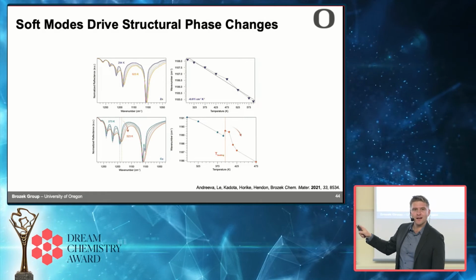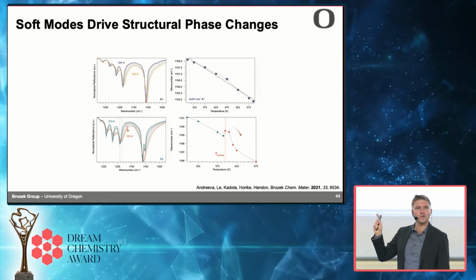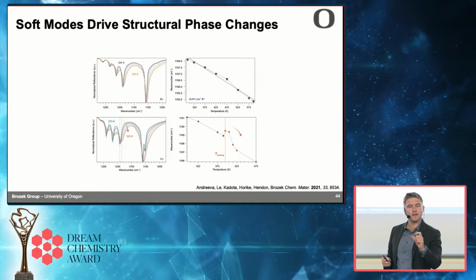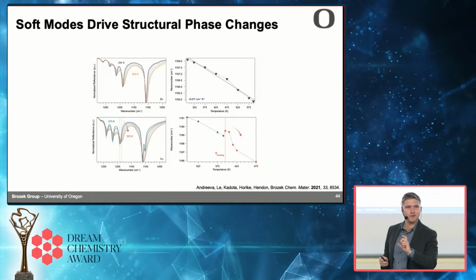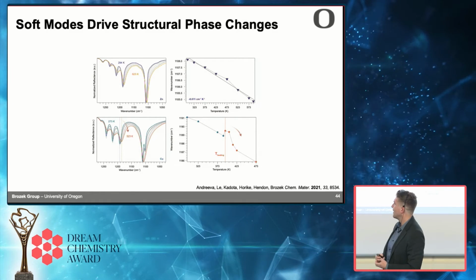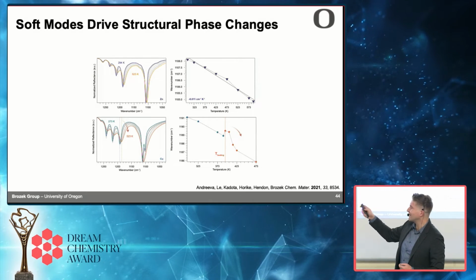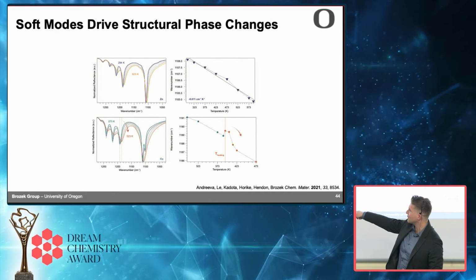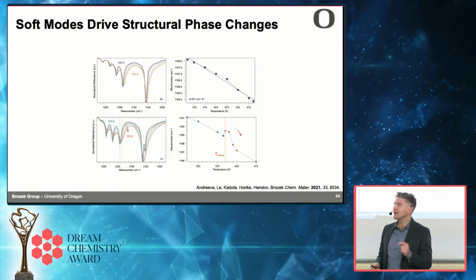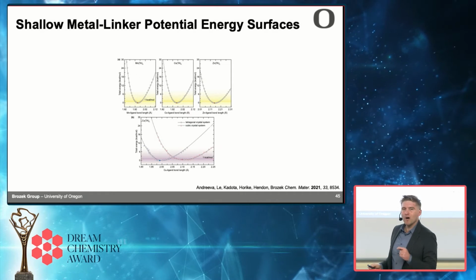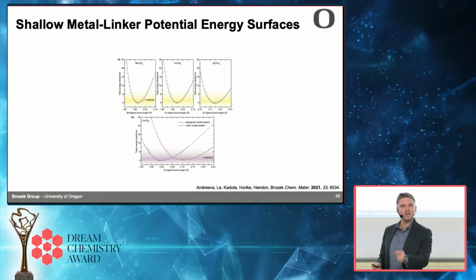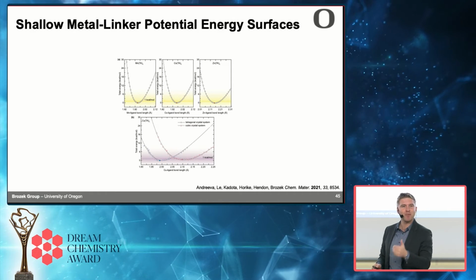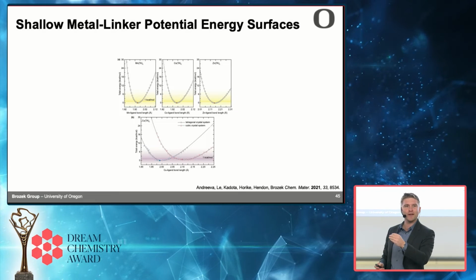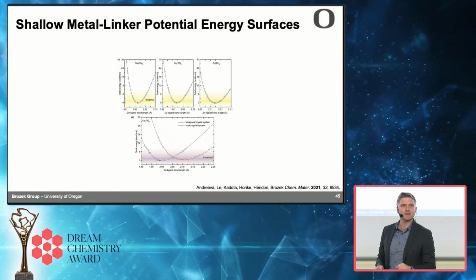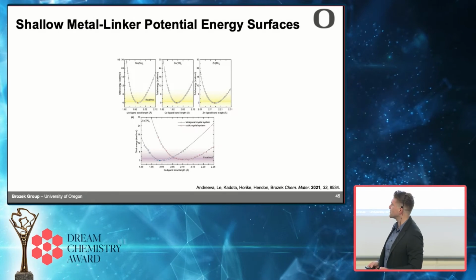Turns out the copper triazolate also undergoes a phase change. It undergoes a crystallographic phase change. It goes from cubic to tetragonal. And when it undergoes a phase change, you also get that inversion. So what this tells us is that MOFs, because they have this intrinsic ability to have these dynamic bonds, if a material can undergo a phase change, that is what's going to act as the mechanism of what causes the phase change.